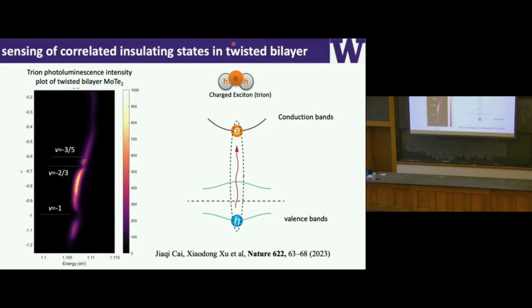Now we go look at these twisted MoTe2 bilayers. And I look at the trion luminescence again as a function of filling number, on the vertical axis. You will see that at these fractional states, the luminescence actually quenches a little bit. We have the 3/5 state, we have the 2/3 state, and at the integer filling -1, we see the same thing again. So this tells us that we have a simple optical readout of the fractional states. In fact, that's how we initially found this state, through optical measurements.